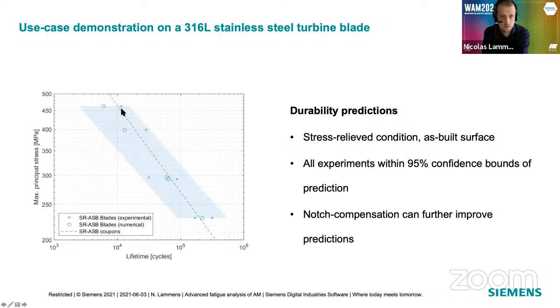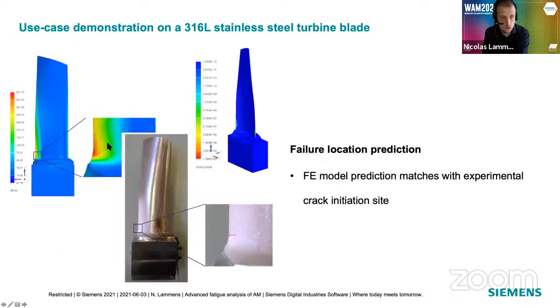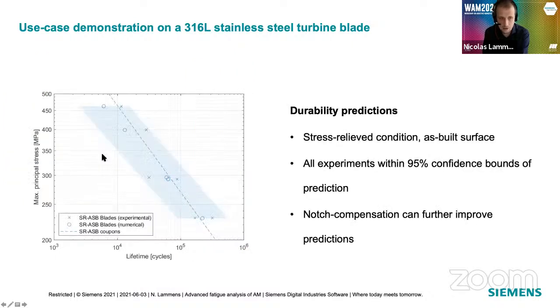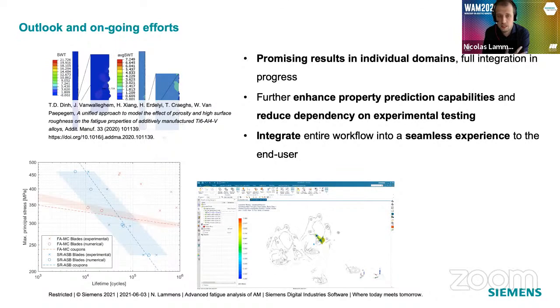So you see that all the test points are within the 95% confidence interval of our prediction, which is a very nice result, especially taking into consideration that if you look at this picture, you see that we have very strong stress concentration. And normally you have to account for that. You have to compensate for the notch effect. And we did not implement this yet in this study. So we are confident that if we would implement this notch compensation, our prediction would match even better with our experiments. So that's a very promising result, but of course, it doesn't mean that we are there yet.